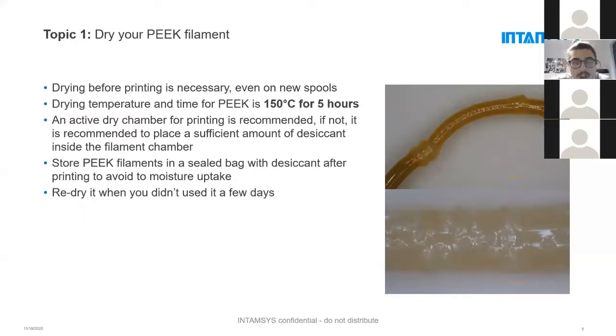If you don't have this, you should place a sufficient amount of desiccant inside of the filament chamber to make sure that you avoid moisture uptake as much as you can. When you are finished with printing, take your filament out of the printer again and put it in a sealed bag with desiccant inside to avoid any moisture uptake. And again, when you start with printing, even if it's only 2 or 3 days, re-dry the material. It will definitely take moisture up, and this has a big influence. This is also what you see here on the pictures, that the material really starts to foam up, gives you bad control within extrusion and also really less strength in the part.